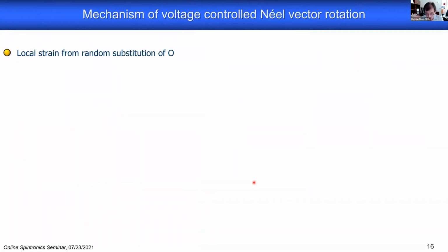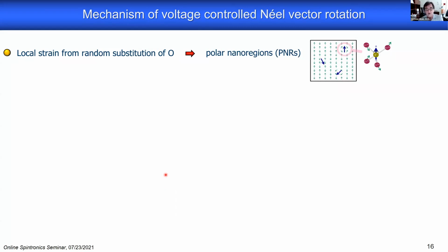Okay, now I come more or less to the end. So I would like to now discuss what we think is the mechanism that gives rise to this 90-degree rotation. So here's the chain of events that happens. We think we have local strain due to the random substitution of the oxygen by boron, which creates these BO4 tetrahedra with boron displaced, creating local nanopolar regions. Now, if you apply an electric field to that system, these existing dipoles, similar to dipoles in water, would orient with the field and create a macroscopic polarization.